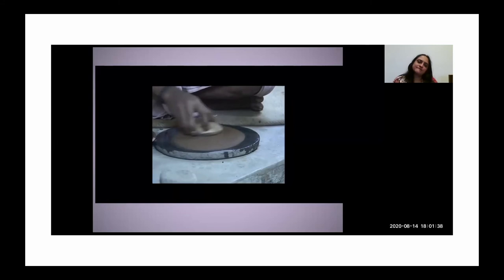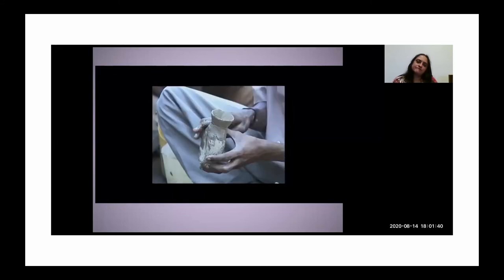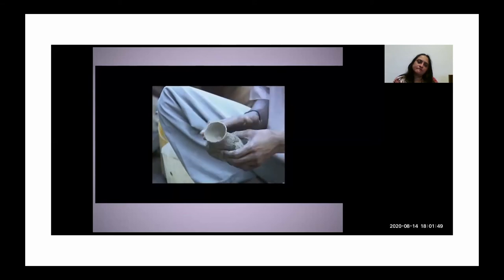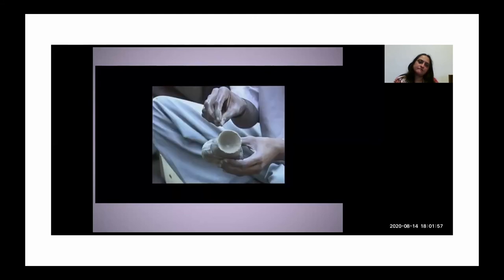As you saw, these two processes, the disc mold being made here with a slip, and then putting the molds inside. And he's also making a hole here for the gases to escape, because that hole is very crucial for the gases to escape, because otherwise the trapped gases will spoil the casting. It will form bubbles.